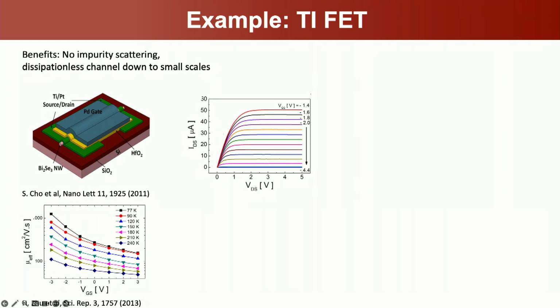The problem here is if you look more closely at the numbers, you can see that the saturation current is actually quite low, and the mobility is very low. The mobility is something like 20 times lower than you'd get for a silicon transistor. And this is a little disappointing because on the one hand, it seems like you have this dissipationless channel and you should get this really high conductance, which you do relative to the size of the thing. But I think as someone mentioned, you also don't have very many electrons. And so your mobility is killed by the fact that you just don't have many carriers in these systems.